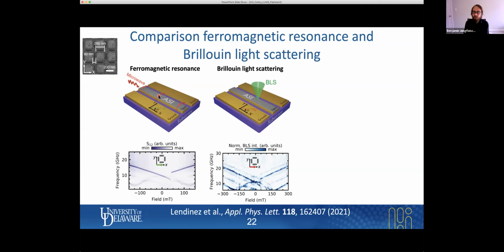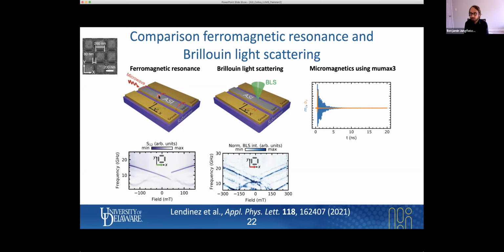So to confirm this further, we used micromagnetic modeling, and there is a package called MuMax3. You can run this on your computer, GPU accelerated. What we do now is we define the same type of lattice, same dimensions. We use one vertex with periodic boundary conditions, and we now apply a sinc pulse with a cutoff frequency of 50 gigahertz to the system, and that is shown here in orange.